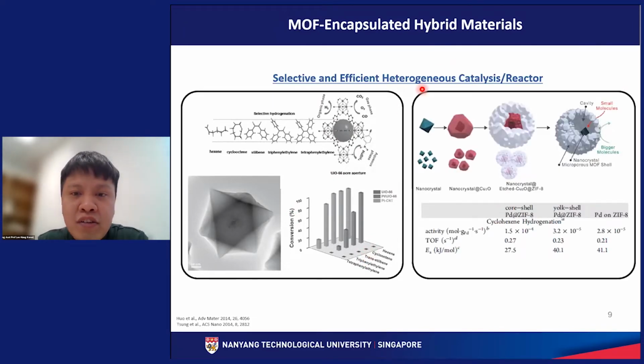Okay, so in this case, we have the yolk shell structure, whereby the MOF is the shell and the catalyst is the yolk. Again, this concept utilizes the pore aperture to differentiate between big molecules and small. So only small molecules are able to penetrate through the MOF material to reach the embedded catalyst.